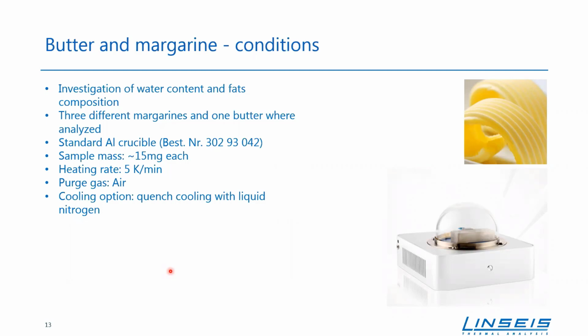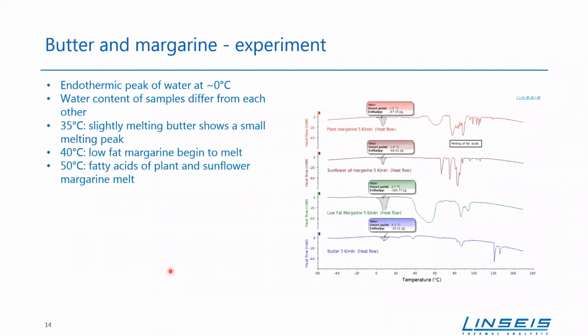The purge gas simply was air. But for this investigation, we need a cooling option, so we were using the ChipDSC 10 for this reason. We've chosen the quench cooling option with liquid nitrogen. So this is now the result. What you can see here is we had some endothermic peaks. First of all, of course, we can see the water peak. And if you're wondering why the enthalpy differs, of course, the water content is different for each sample. Through this result, you can, for example, simply calculate the water content because you have the literature value for the enthalpy of melting water.